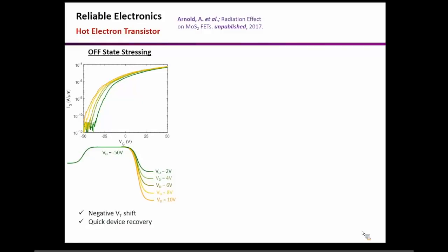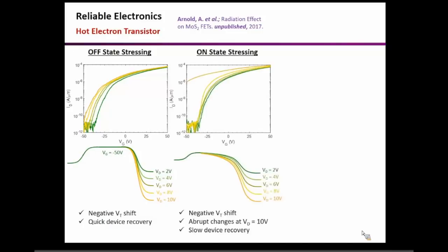Now you can see that if we bias this device in the off state and then apply these large stressing voltages, you start to see a little bit of shift of the threshold voltage in the negative direction. But then it can be very quickly recovered. If you wait for a certain period of time, the device actually gets back to its original state. Now, if you do the same experiment, but in the on state of the device, then you start to see a similar effect, but something drastic happens at 10 volts in the on state. And that's because you have a different band alignment or band structure.